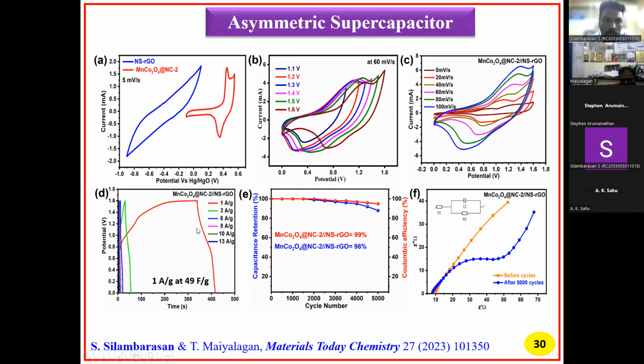And then figure D has the charge and discharge performance at 1 ampere per gram, 49 farad per gram. We measured here. Then the Coulombic efficiency in figure E is 99%, and the retention percentage is 96%. Then figure F is the impedance spectroscopy we measured before cycling and after 5000 cycles.